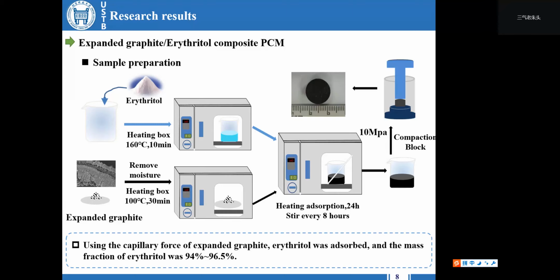Finally, press the tablet with a diameter of 13 mm and a thickness of 4 mm, using the capillary force of expanded graphite. The mass fraction of erythritol was 94% to 96.5%.